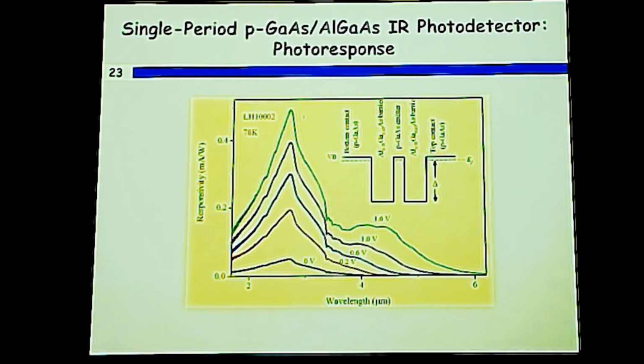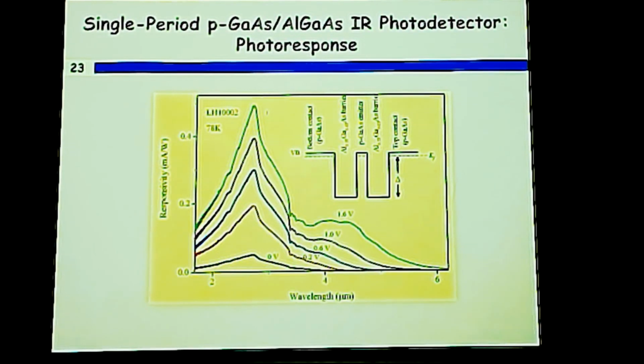Not in this one, because the thermal mechanism is slightly different. There are different materials. Gallium arsenide is also shown to have a thermal detection mechanism, but they are basically different. The mechanism is bolometer type, which means with the incoming infrared radiation, the resistance of the device changes, and that gives a measure of change in the current. So that is a slightly different way. In this one, the carriers are photo excited to a higher energy level, and collection of those carriers gives the external signal. But there is a thermal mechanism too. In those, the photocarriers are not excited, but the resistance of the device changes with the radiation. So mostly vanadium dioxide or similar materials are bolometer type thermal detectors.